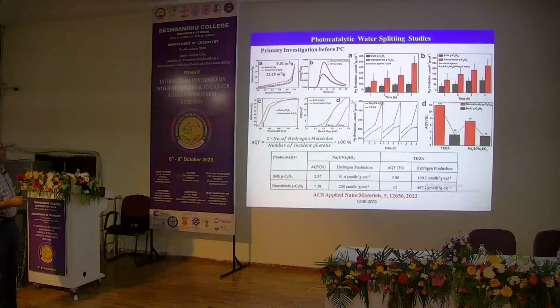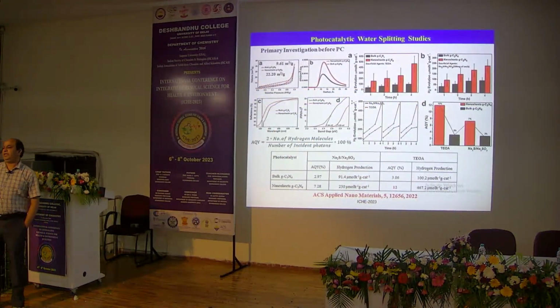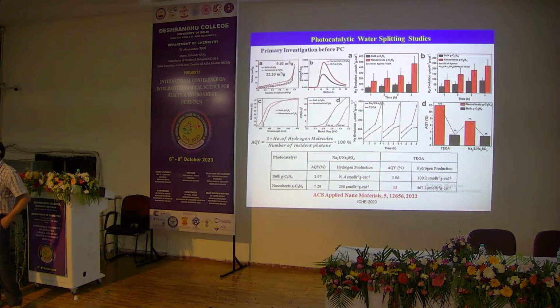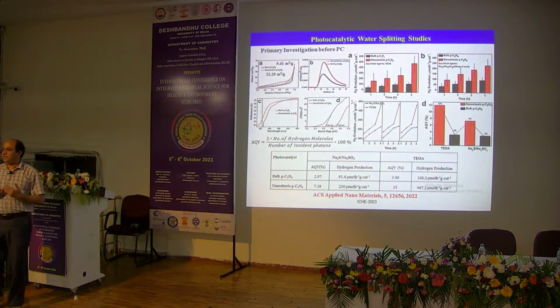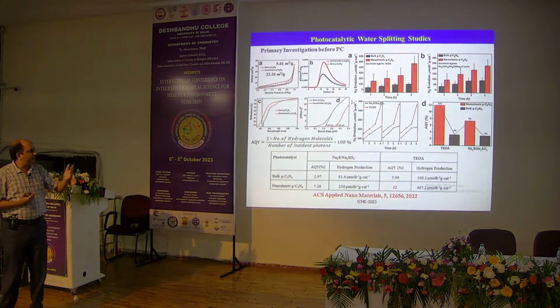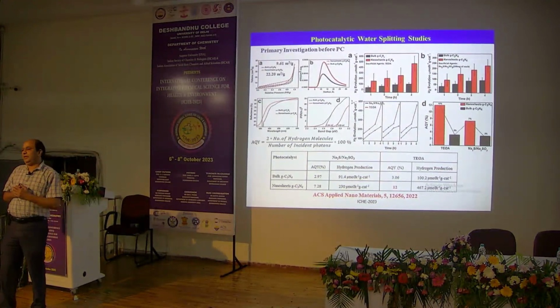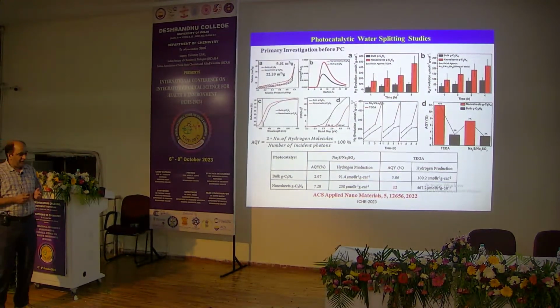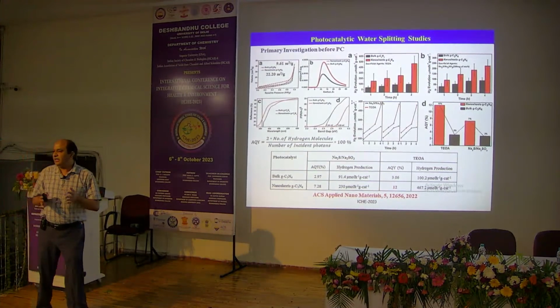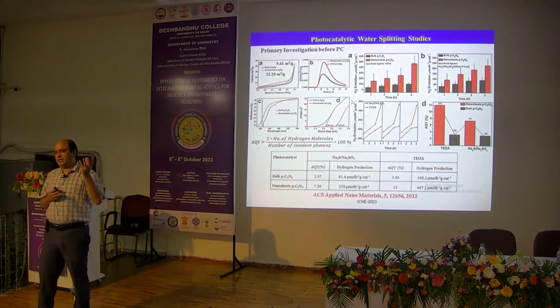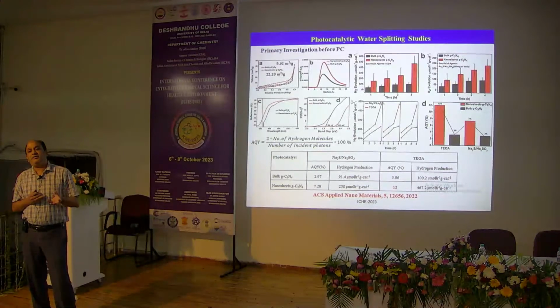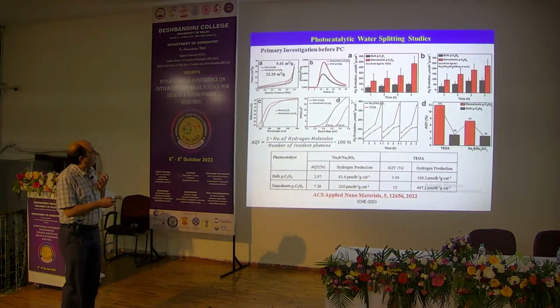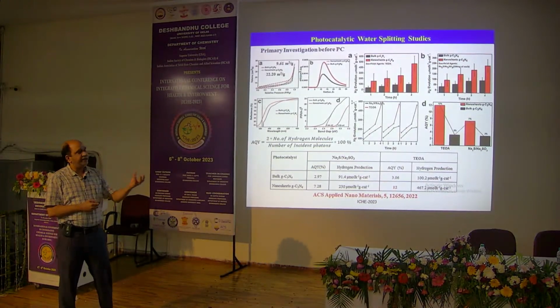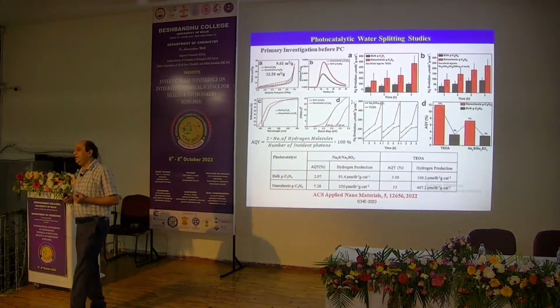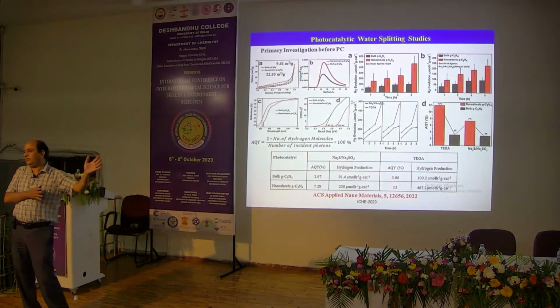So these are the primary investigations like the surface area and the optical band gap, because if you have the primary investigation, then you can directly go to the water splitting measurement. For the water splitting measurements, we made two different sets of reactions. In one set of reactions, we take sodium sulfide and sodium sulfite as the sacrificial agent, and in another set of reactions we take triethanolamine as the sacrificial agent.